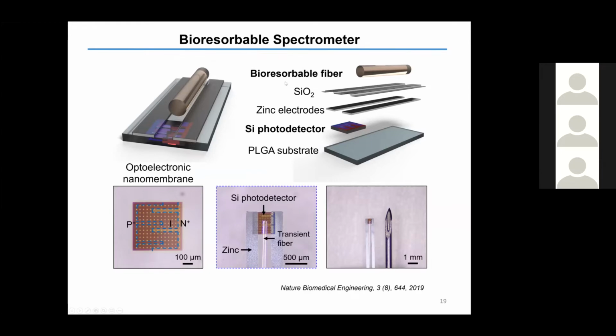The first one is a bioresorbable fiber made of PLGA, an FDA-approved biopolymer, for delivering light with a certain wavelength to the sensing probes. The second is a bioresorbable photodetector made of nanomembranes of doped monocrystalline silicon for generating electrical signals in response to the transmitted light. And the last component is the electrodes made of thin films of zinc for electrical readout. We also use a thin layer of silicon dioxide for encapsulation to ensure stable performance over a controlled period, which is followed by full device bioresorption.